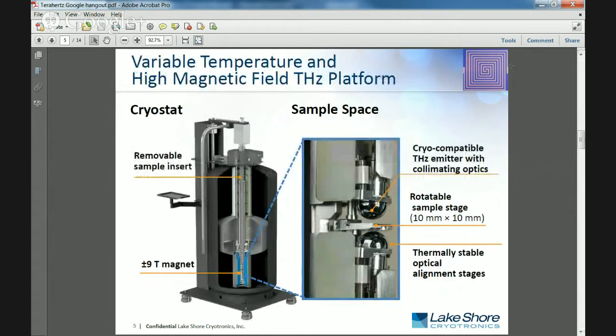Yeah, so this has been a two-year process of development, where we've really had to start from the ground up. One of the real key elements here is these in-situ cryogenically compatible emitters and detectors. What we've done is placed a terahertz emitter and terahertz detector inside the cryogenic and high field environment, in proximity to the sample under test. What that allows is a user can come in and place the sample easily in there without having to align large amounts of optics.